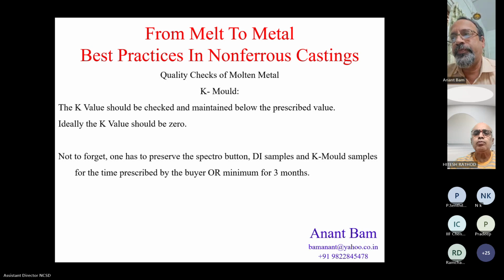K mold. The K value should be checked and maintained below the prescribed value. Every customer should be recommending to you what the K value should be. Ideally, the K value should be 0. Not to forget, one has to preserve all these samples, spectro button, density index samples and K mold samples, for the time prescribed by the buyer or for a minimum of 3 months.